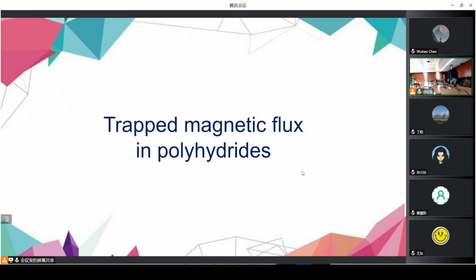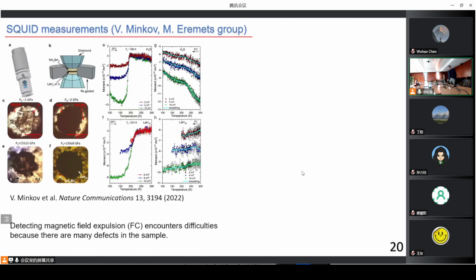And the last part of my presentation, I will finish soon. It's about trapped magnetic flux in polyhydrides. It was recently found, and it's a great discovery in my opinion, made by Vasily Minkov and Mikhail Eremets' group in Mainz. They investigated polyhydrides like H3S and LaH10 using a SQUID methodology, using a special, very tiny SQUID with diamond anvil cells, so very small samples of polyhydrides. They found quite a clear response in magnetic susceptibility in zero field cooling.